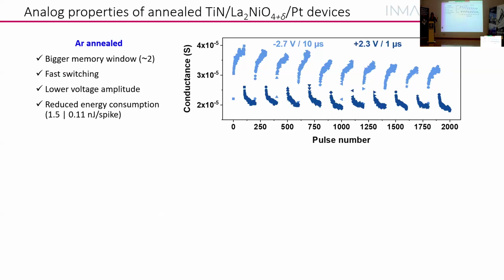Then we did all these steps of what is called potentiation and depression curves. So you apply a number of positive pulses and then negative pulses, and you measure each resistance state that you obtain, and you repeat it many times to see if it's reproducible. So this is what we obtain.